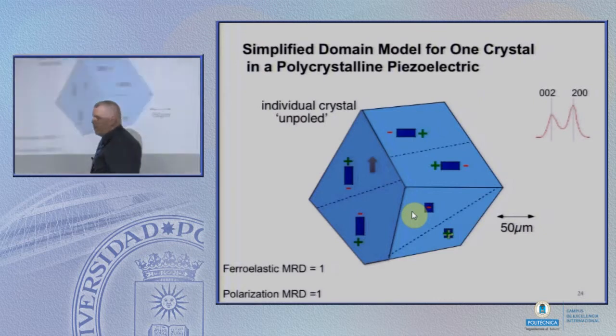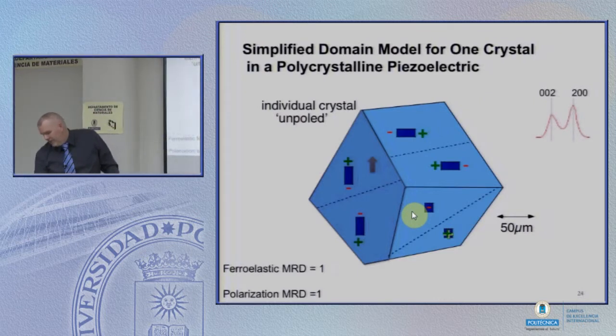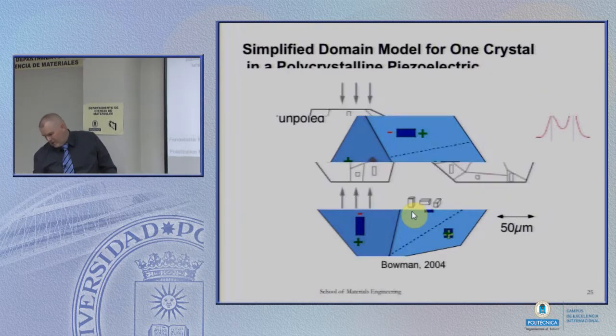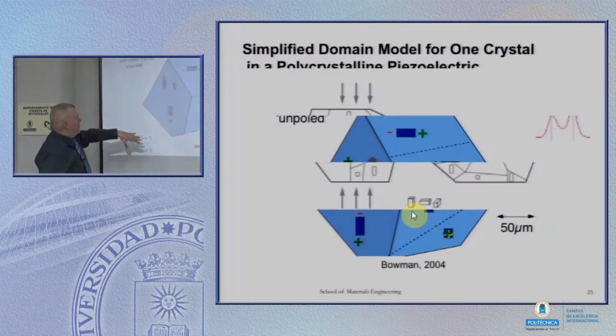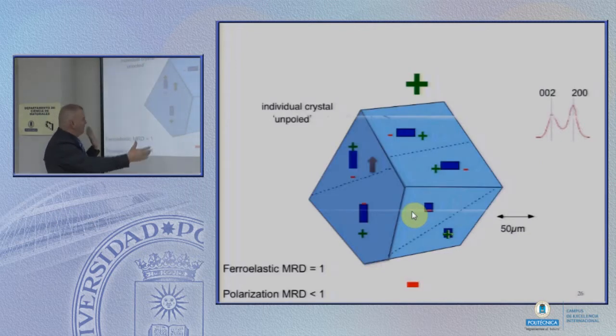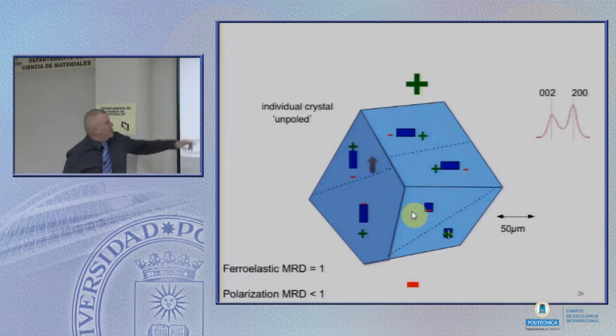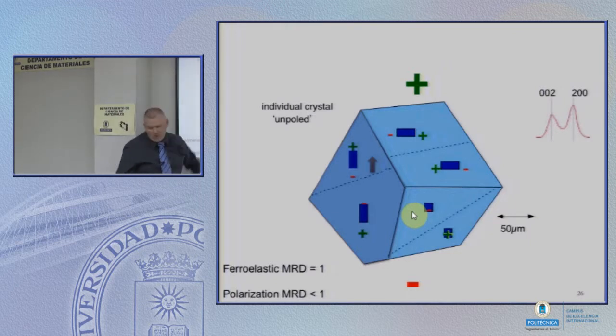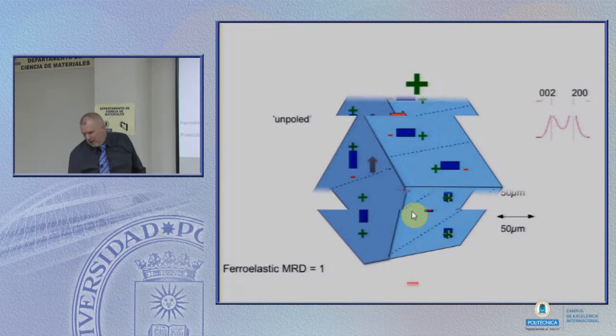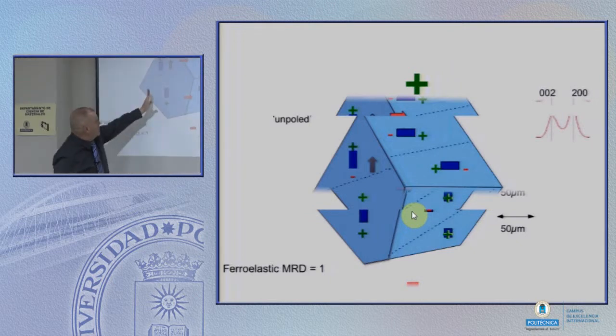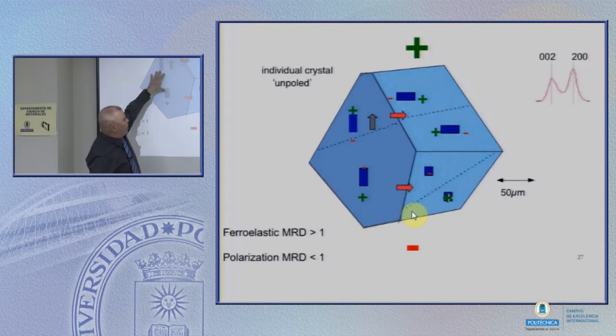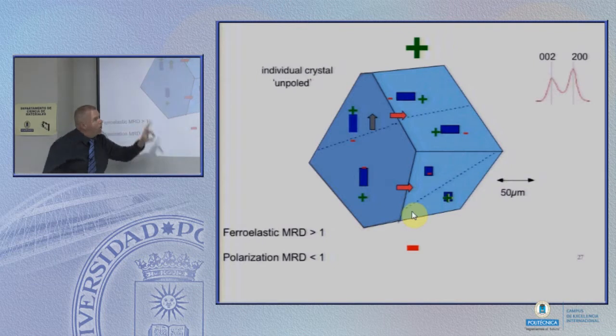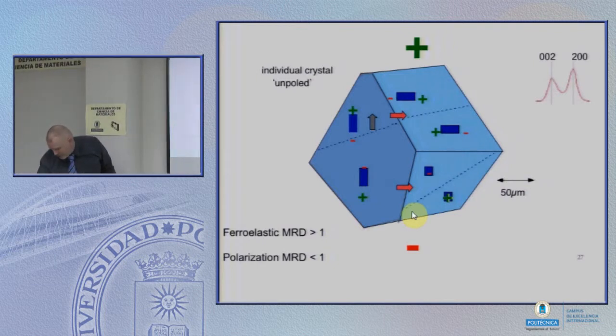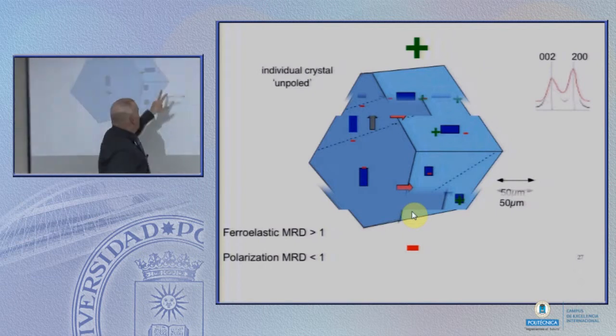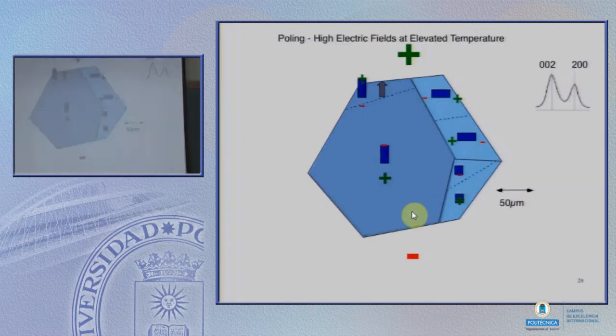What happens when we pole the material, since we apply a large electric field to it, right? And we want to get the domain boundaries to move, so we start the process here. I've actually started to move some of these boundaries from the prior image and go a little bit further as we start to then move this boundary and make this larger, because the electric field applied here will get more response from the material. If we do that, we start to shift these peaks around. So we end up with this flipping of the amounts.